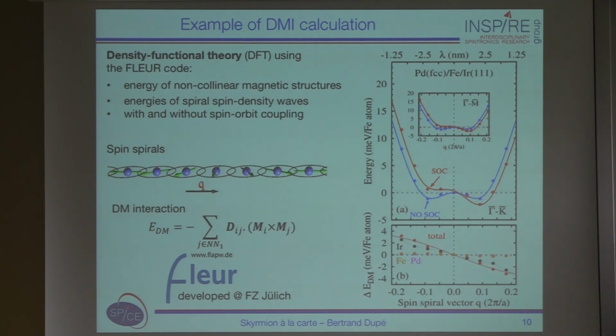So DFT is a very nice technique because you can look very precisely at the origin of the energy. And so you can actually decompose the energies coming from the spin-orbit coupling depending on the layers. And that's what is shown here. So this is the variation of the spin-orbit coupling energy as a function of the spin spiral vector for a left-rotating spin spiral and a right-rotating spin spiral.